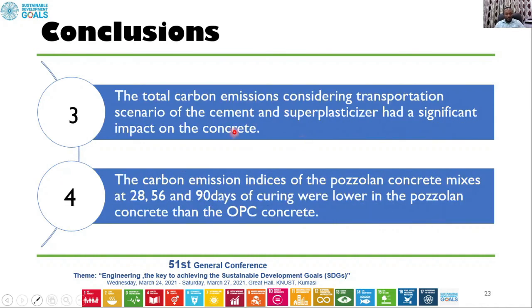So the third one, when we consider the transportation scenario, it actually increases the total carbon emission of the product. And then the fourth one is this: the carbon emission indices of pozzolan concrete mixes at 28, 56, and 90 days of curing were lower in the pozzolan concrete than the OPC concrete.